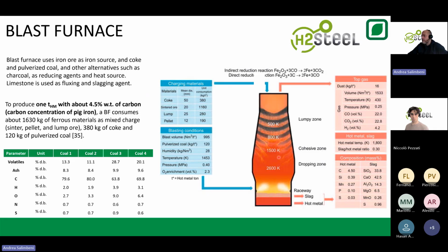The coke has a double role of producing CO while gasifying, but also to maintain a porous layer between the iron ore which is injected in the furnace, so that the gas can pass through and the production of gas can enable the reduction of iron ore into iron. To do that, the coal used is considered high quality coal, where the volatiles are quite low, between 10 and 20%, and the carbon content of the coal should be high. Between 65 and 80% is something that is acceptable.